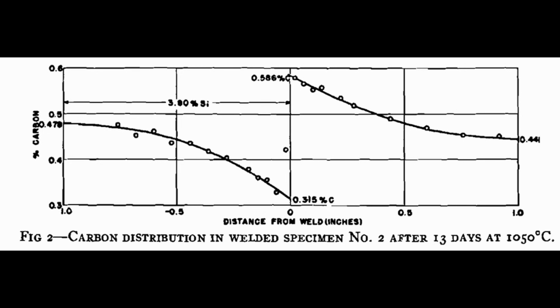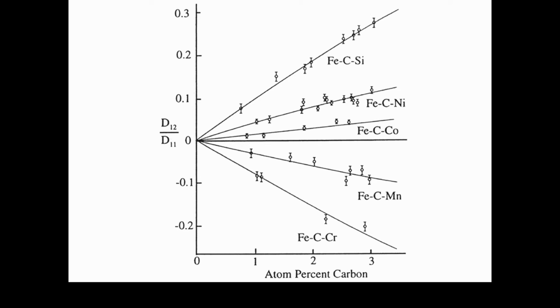So the silicon had changed the interaction between the steels so that the carbon was preferentially going to the low silicon steel. And different elements can have different effects. Silicon is the strongest for making carbon diffuse away. Chromium has the opposite effect, where it makes carbon want to go towards that steel. And so if you forge welded up to a non-magnetic stainless, that just means a stainless with high chromium and nickel, the carbon would diffuse preferentially into the stainless steel. So there would be even a little bit more carbon diffusing into the stainless.